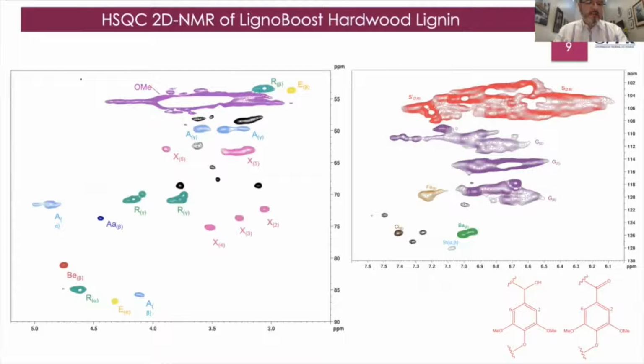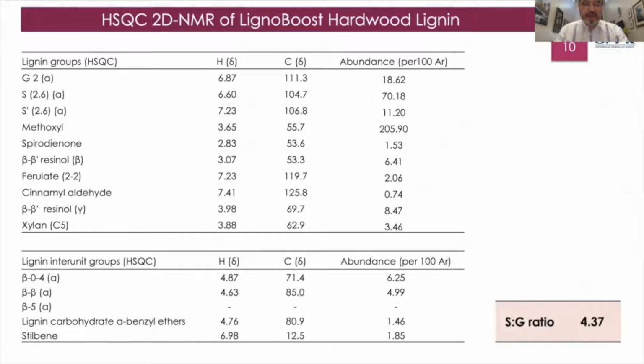Lignoboost hardwood lignin was also characterized by HSQC 2D NMR experiments, and these are the two spectra obtained for the aliphatic and aromatic regions, to the left and to the right, respectively. Results indicated the occurrence of a variety of functional groups, some oxidized groups as well, primarily syringyl, from which a ratio of syringyl to guaiacyl of 4.37 was obtained. Also, it was clear that the low beta-O-4 linkages in those lignins was coherent with their low molecular mass.